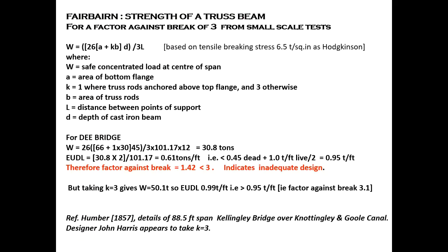Now there have been other theories. Fairbairn had done some tests. This is after the failure, and he came out with a formula which is very much based on the Hodgkinson formula, but adds in the effect of the chains. You can see there's a factor K which takes account of whether the truss rods are anchored at the end above the top flange or below it.